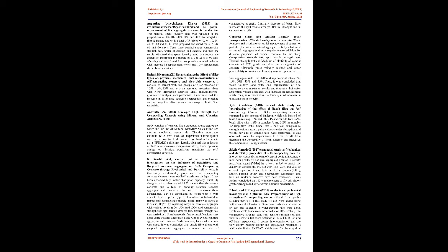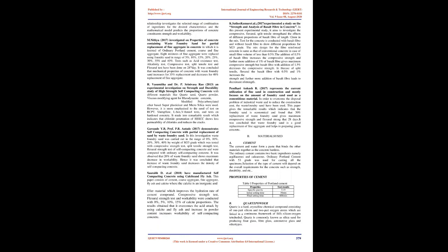Hafiz E. Elyamany, 2014, et al. evaluated the effect of filler types on physical, mechanical, and microstructure properties of self-compacting concrete and flowable concrete. It consists of cement with two groups of filler materials at 7.5%, 10%, and 15%, and tests on hardened properties, along with X-ray diffraction analysis, SEM analysis, and thermogravimetric analysis, were performed. It was evaluated that an increase in filler type decreases segregation and bleeding, and no negative effect occurs with non-pozzolanic filler